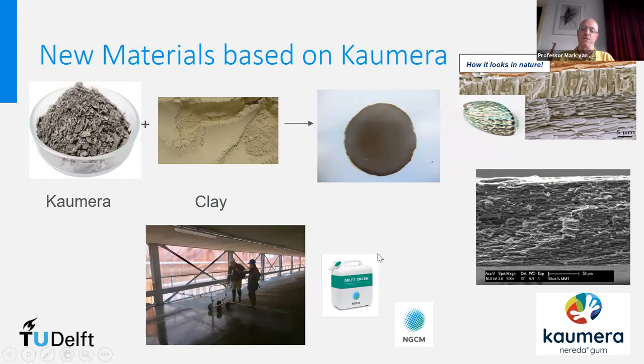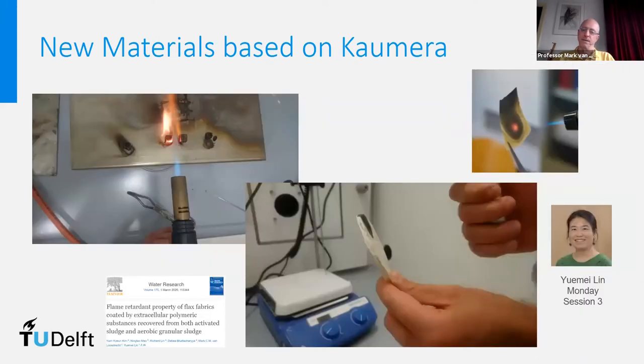And that's the first application, which is on the market. It's nicely called the Delft Green, marketed by this company NGCM, which if you spray it on the floor of, like, parking lots in the construction here, it improves the hardening of the cement. And it means that you can use about 10% less cement and have the same protection of the steel and strength of the structure. So a very interesting application due to the fact that it's shielding off.